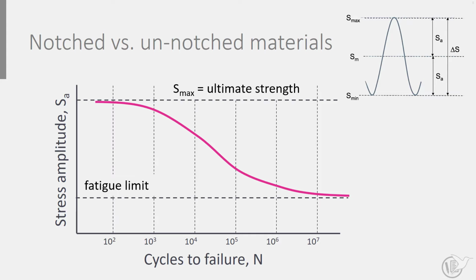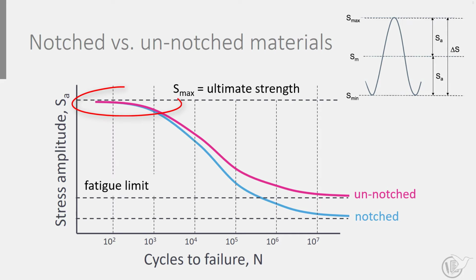In a previous video I explained that ductile materials are less sensitive to notches. Now this can be illustrated here with the two S-N curves, where the upper asymptote effectively is the same for both unnotched and notched materials. There is however an effect visible on the lower asymptote. In fatigue loading with low amplitude stresses, the entire notch vicinity remains mostly linear elastic, which means that the sensitivity to notches is observed. This is illustrated by the lower fatigue limit for notched materials. The reduction of the fatigue limit can be calculated by taking the fatigue limit of unnotched material and dividing by the stress concentration factor Kt. What can be concluded from this illustration is that at the same amplitude stress, a notched material has a lower fatigue life compared to an unnotched material.